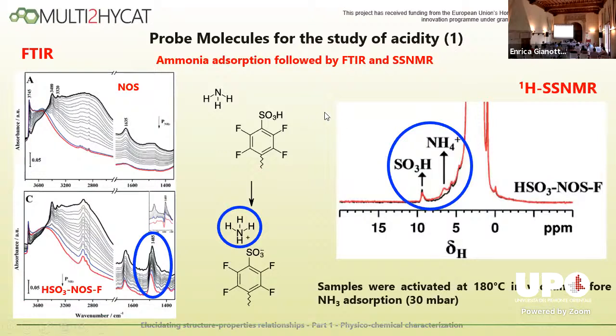What is really relevant in this case, because we are talking about acid catalysts, is to characterize the acid sites. In this case, it's not as simple or as straightforward as when acid sites are part of a zeolite, for example, because there we can send probe molecules. For example, carbon monoxide didn't give very interesting information, because the signal of carbon monoxide adsorbed on silanols was covering all the other possible signals, and there was no direct evidence of interaction with the sulfonic groups. On the contrary, the adsorption of ammonia gives rise to the very specific signal of the ammonium ion that we can monitor in the low frequency region of the infrared spectrum. But we can also monitor it by solid-state NMR in controlled atmosphere.